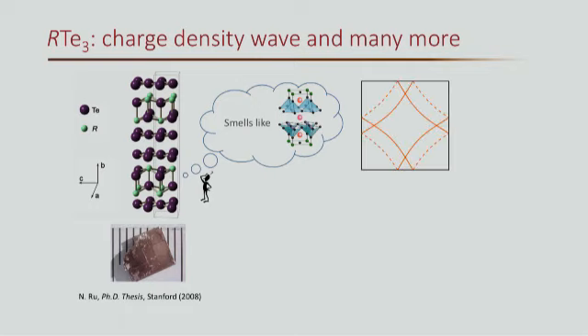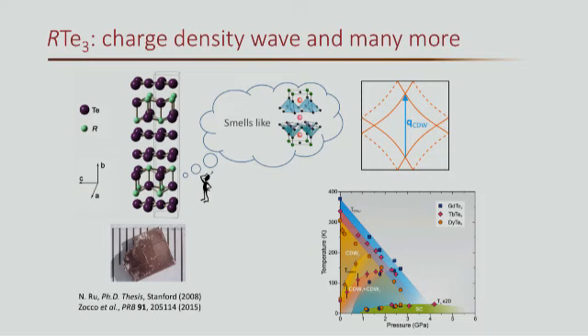As I said, the Fermi surface here is pretty much determined by the 5p orbitals of the tellurium atoms inside these square lattices. And here is just showing a schematic from first-order tight binding calculations. And here I just want to label the wave vector that forms the charge density wave for the first transition. Very similar to many other charge density waves, as experimentalists you probably expect the charge density wave is not always alone. And in fact, for this particular material, if you look at the phase diagram, if you either apply pressure or chemically dope it, some other phases, such as superconductivity, can also emerge.